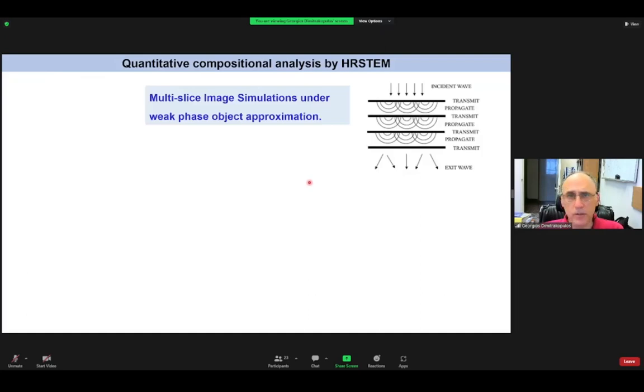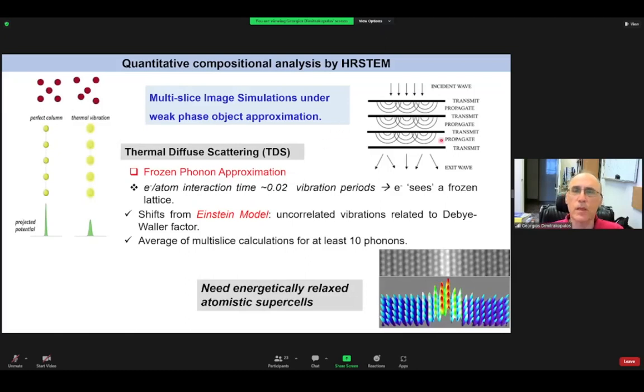How do you do image simulation? There are a couple of approaches. One is the Bloch wave, but the more common one is the multi-slice image simulation. You consider your crystal to be composed of many slices, and each slice you take to be like a weak phase object. So it's all in the books. I'm not going into any detail on this one, but for STEM, you need to take into account also the thermal diffuse scattering. In other words, the atoms are moving. And in order to take into account this thermal vibration of the atoms, we use what is called a frozen phonon approximation.